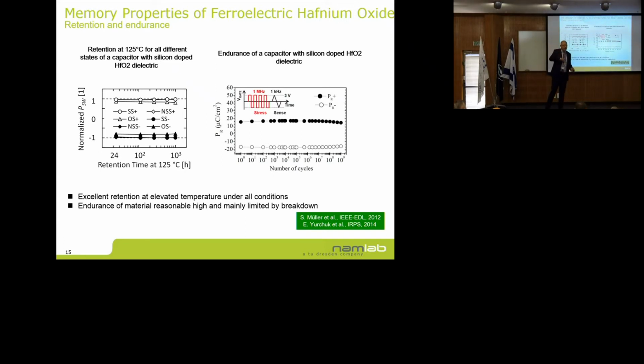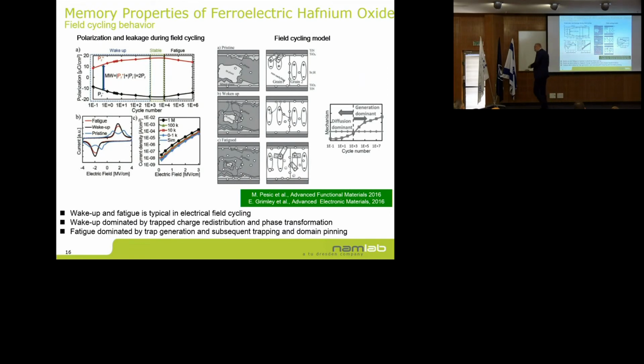And now there's a drawback of the high coercive field, because typically cycling ends by hard breakdown, because you're cycling pretty close to the breakdown field of the device. So this is one of the limitations. The cycling is very comparable to what you see in other ferroelectrics. First you see a wake-up, then you see a stable phase, and then you see a fatigue.